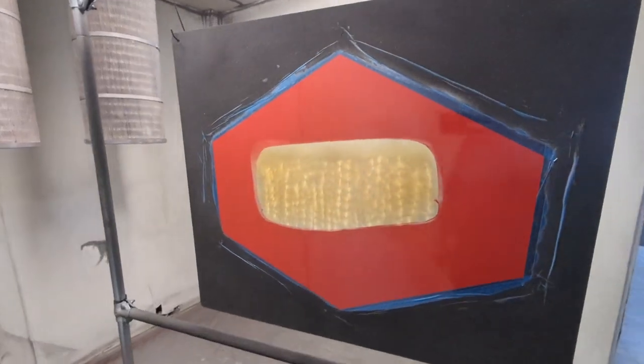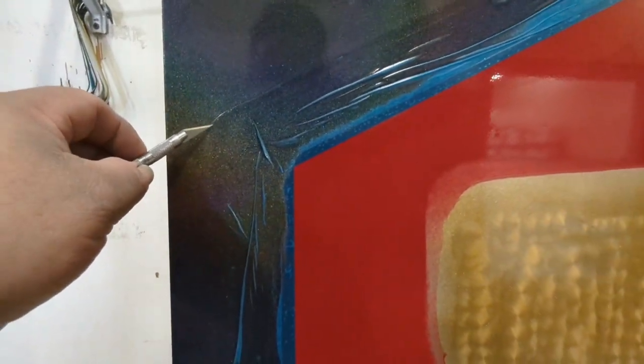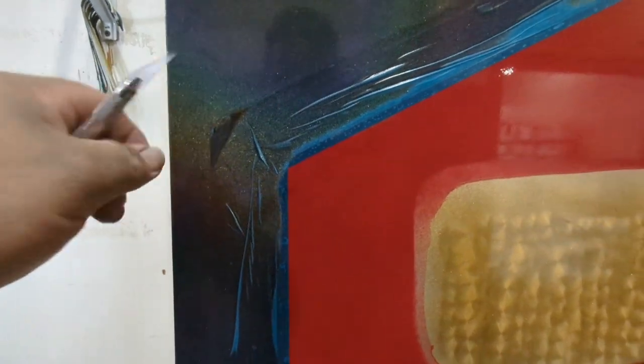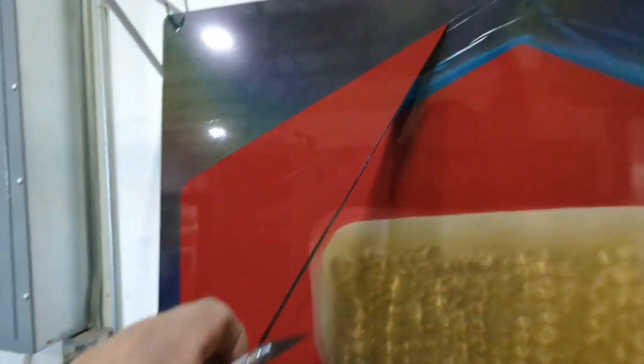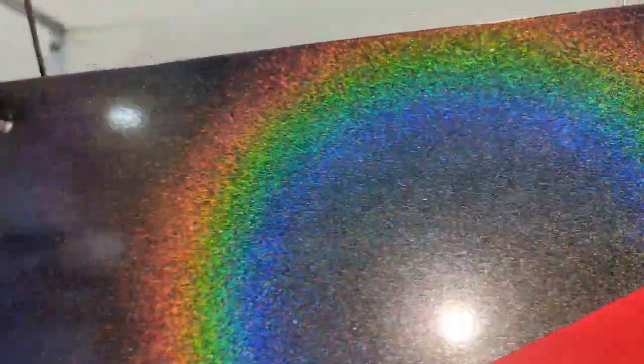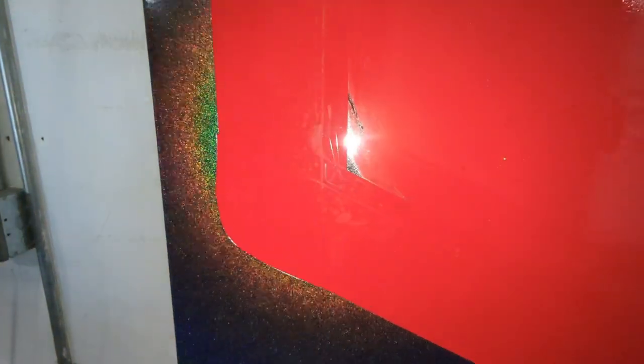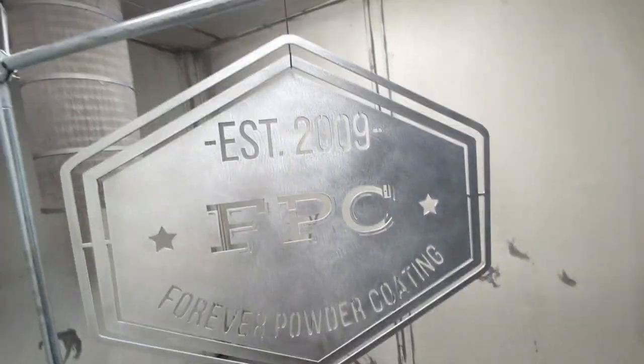So, this thing's all ready for the oven after I vacuumed and wiped all this down. So, it's just going to go in for a flow out so I can pull the tape off, essentially. I've still got more to do. So, this is after I threw it through the oven. Going to be yanking the tape. Going to want to make sure on a project like this, you definitely pull the tape while it's warm. You don't want the powder to be super gooey. You don't want it to get stringy. So, you can do little test edges and make sure that it's not stringing out. As you can see, this comes off really easy when it's warm. Leaves a nice clean line. Doesn't leave any residue. You can see the prismatic flake from Prismatic Universe looking absolutely amazing. The rest of this thing looks good. I mean, all my lines that matter are there. But then there's this. Now, this is a thing where had I masked it all off, this probably wouldn't have happened. This big goof right here. But, luckily for me, I have a lot of play in this sign. I set this up to allow myself to think these lines should not be perfect.